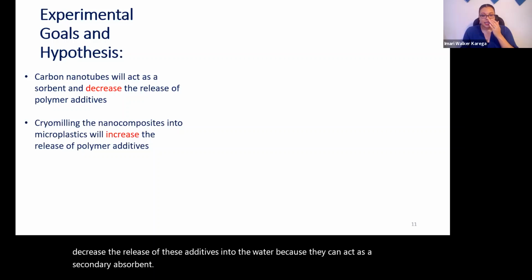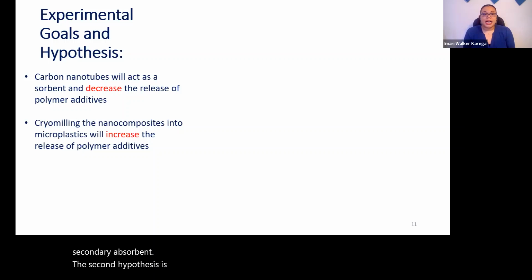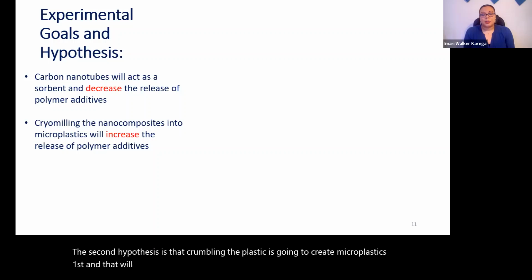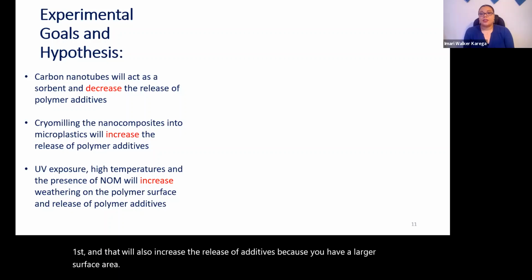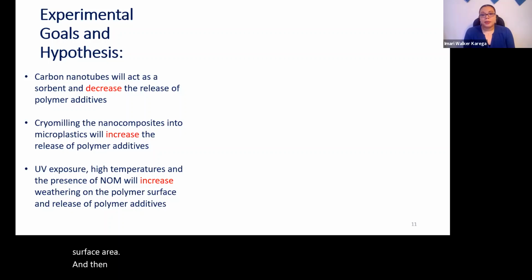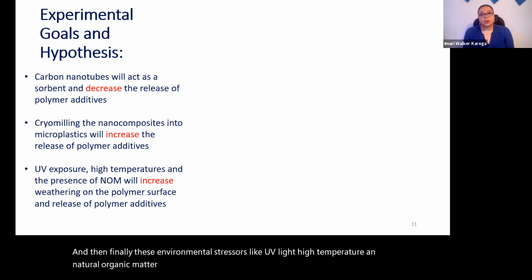The second hypothesis is that cryomilling the plastic creates microplastics, which will increase release of additives due to larger surface area. Finally, environmental stressors like UV light, high temperature, and natural organic matter are likely to increase weathering of the polymer surface and release plastic additives.